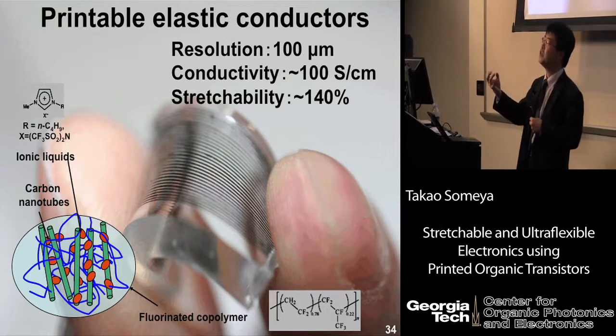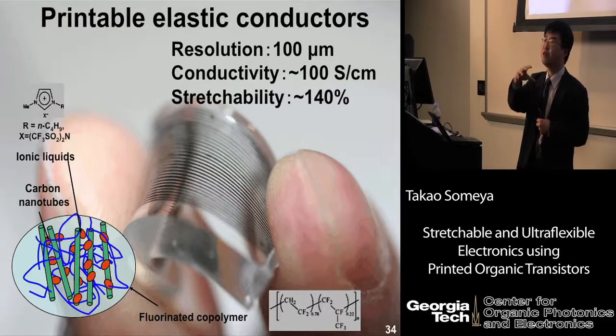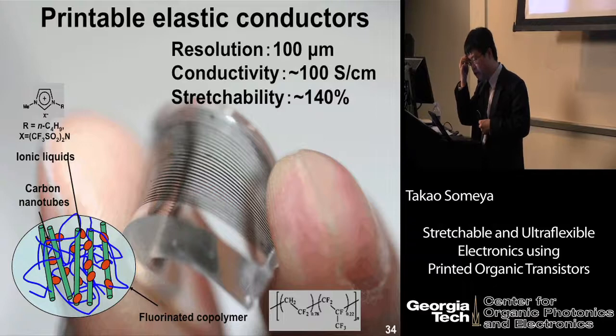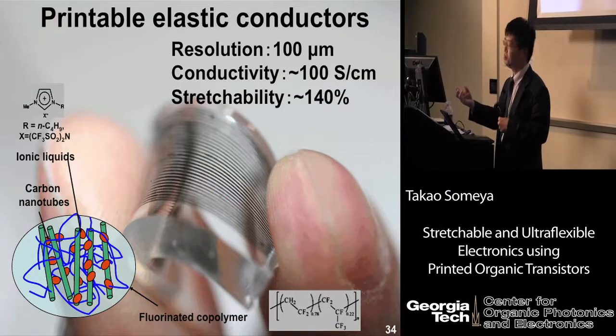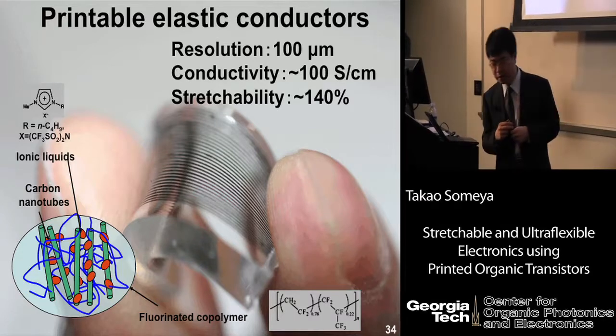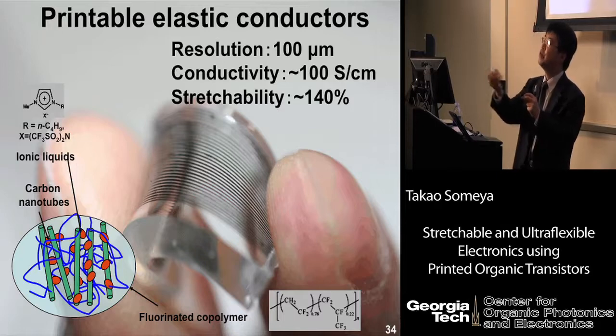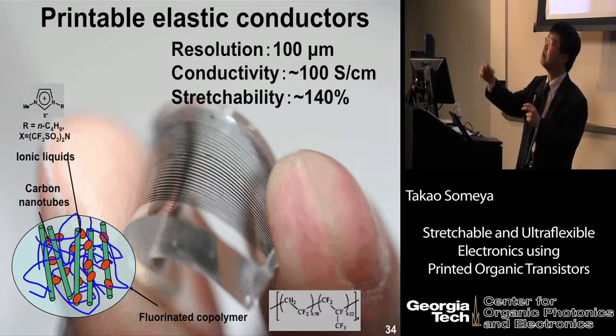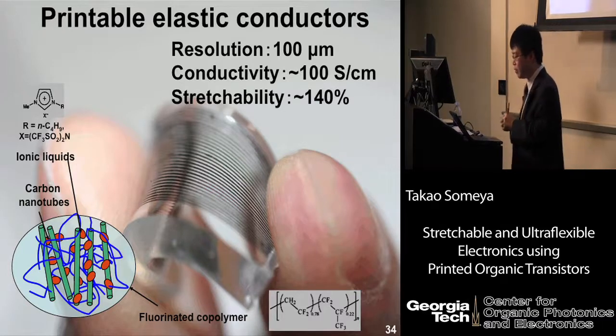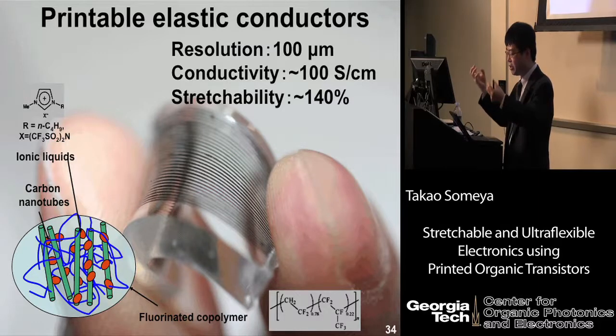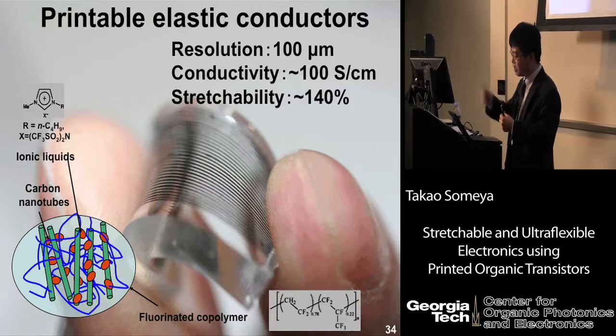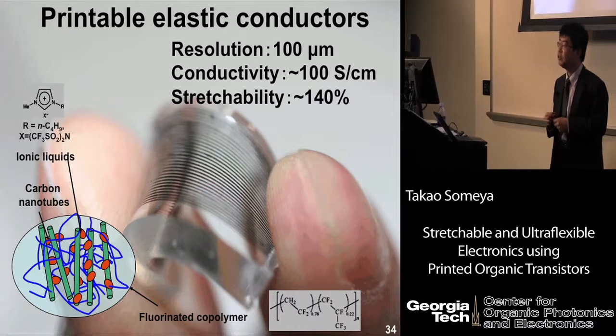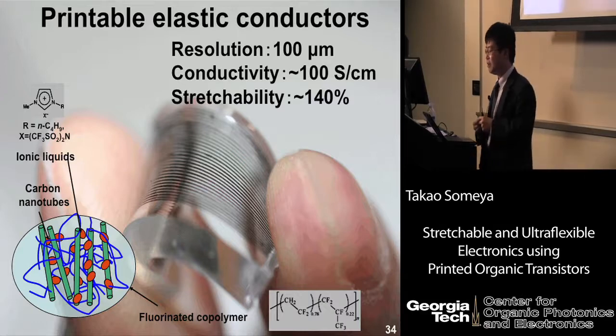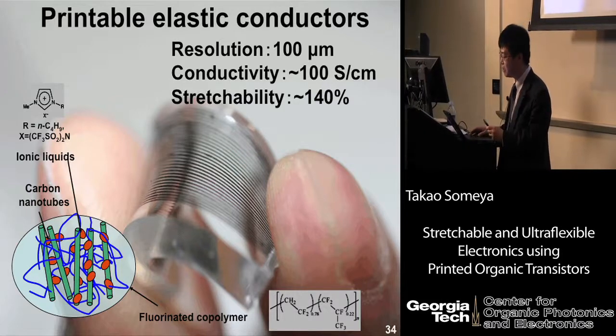Of course, rubber is an inherently insulating material. We have to add some dopant. Here we choose single-walled carbon nanotube as the conducting dopant. However, here is a problem. As many of you know, carbon nanotubes tend to form thick bundles that cannot be well mixed in a rubber matrix. To avoid that problem, we first mix the carbon nanotube with ionic liquid to form the nanotube gel, Bucky gel. Bucky gel can be well mixed in some sort of fluorinated copolymer. In this way, we can make quite high conductivity, or rather the world's highest conductivity among soft materials.